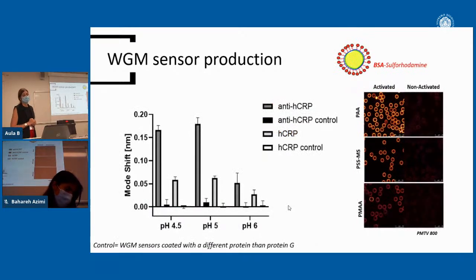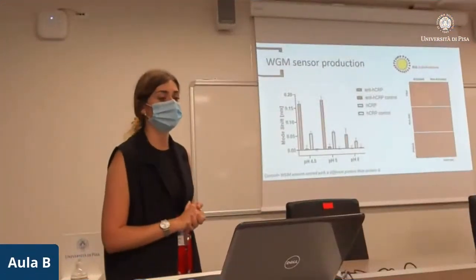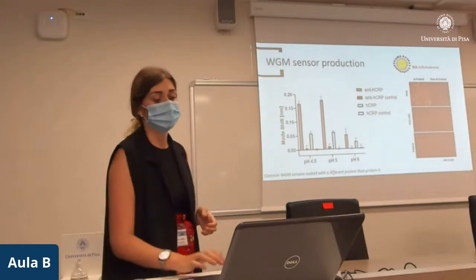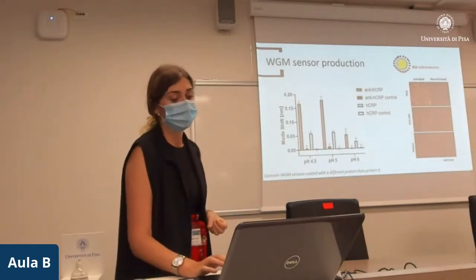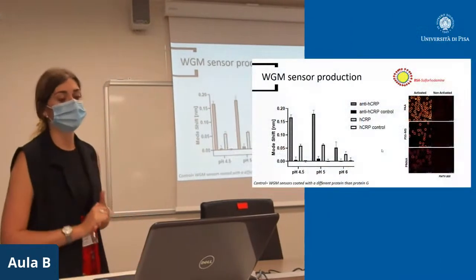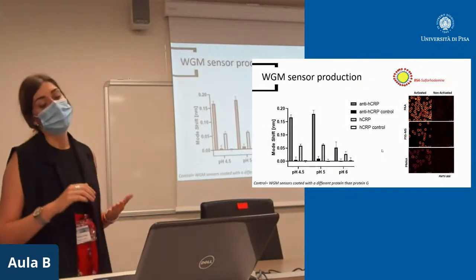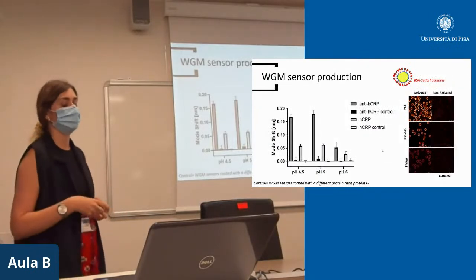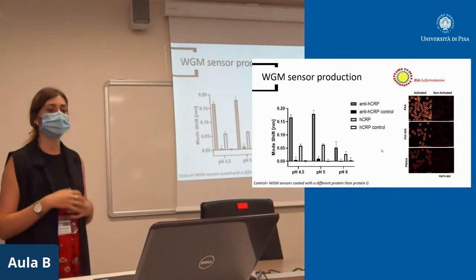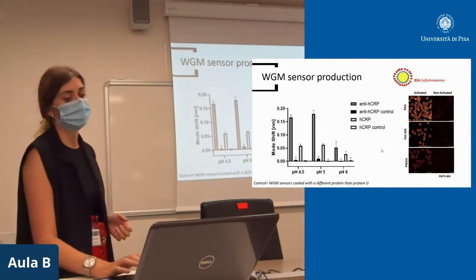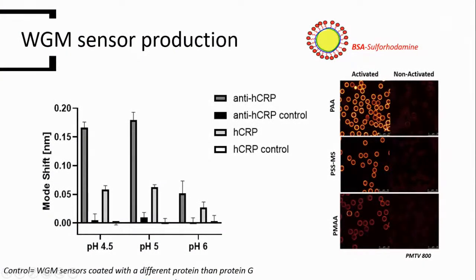And here, it's important to also measure the unspecific binding of the molecules to the sensor. And this is what is shown in this bar plot. When we added the antibody or the antigen to a microsensor coated with different proteins, not protein G, we could not detect any binding. So this means that the binding that I showed you before was really specific to the protein G and to the antibody.